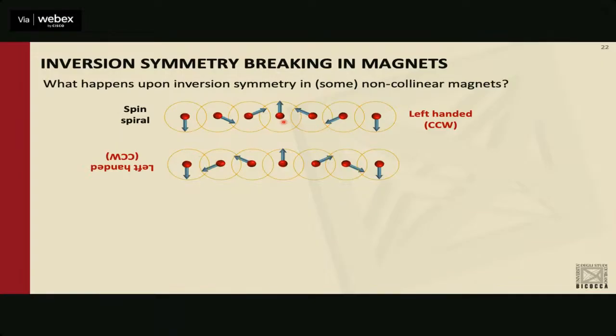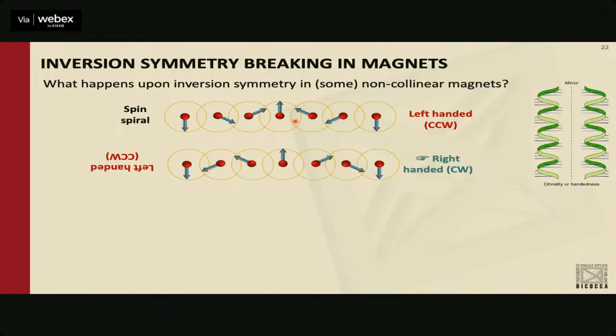And actually a spiral that was left-handed becomes right-handed by inversion symmetry. So these inversion symmetry partners are opposite, and so you basically switch the so-called chirality of spin. So you have a chirality from the upper, let's say, counterclockwise spiral, which becomes clockwise in the right-handed one. So certainly with a spiral, although the atoms themselves would keep inversion symmetry, right? Because the red atom is a red atom here, a red atom is a red atom here. But once you include spin degrees of freedom, then you break inversion symmetry. And so in a non-collinear magnet, you have an additional way to break inversion symmetry.